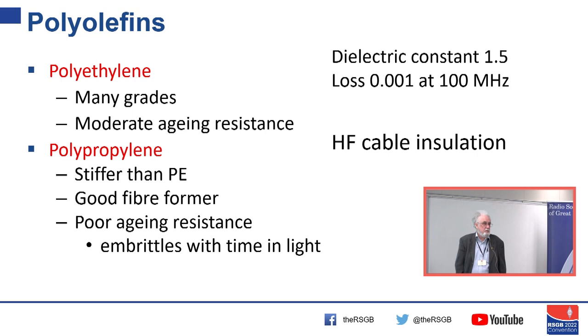It was the material that enabled us to make cables that would carry signals that were usable for radar and TV. It was one of the things that contributed to the Second World War, the development of radar, and the development of radar essentially required the development of polythene to provide the cable insulations for it. Polypropylene is very analogous. It's much stiffer than polyethylene, and whereas polythene doesn't form a good fiber, polypropylene does. You can spin polypropylene and stretch it to make very, very strong fibers, and of course it's the material that's used a great deal in producing all sorts of ropes.